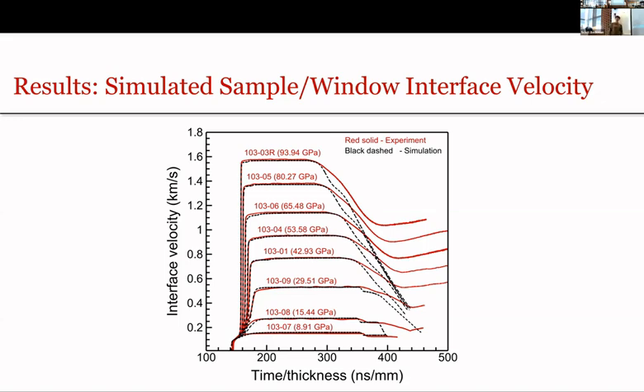That is because prior to the arrival of the release wave, the material is broken, but it's still held together by the pressure confinement. When the release wave arrives, the broken, pulverized material is no longer confined by the pressure because the pressure is released. So the material is able to flow at a lower pressure confinement. And this deformation physics is not included in our current model, but will be taken care of in future work.